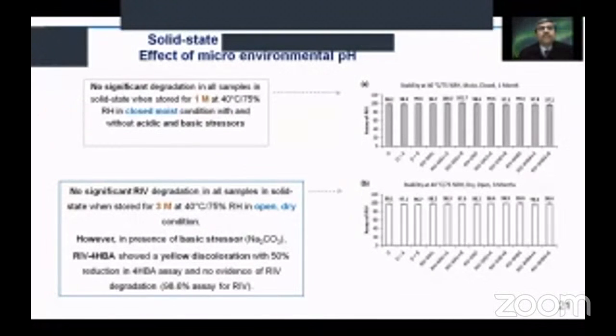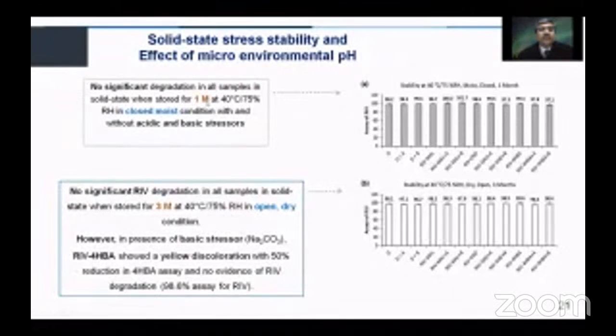The solid state stability and the effect of microenvironment pH was then assessed. There was no significant degradation in all the samples in the solid state after 1 month at 40 degrees Celsius, 75% RH in the closed and moist conditions. No significant degradation in all the samples in solid state when they were stored for 3 months at 40 degrees Celsius and 75% RH in open and dry condition.